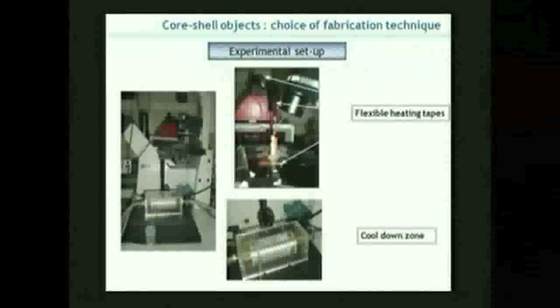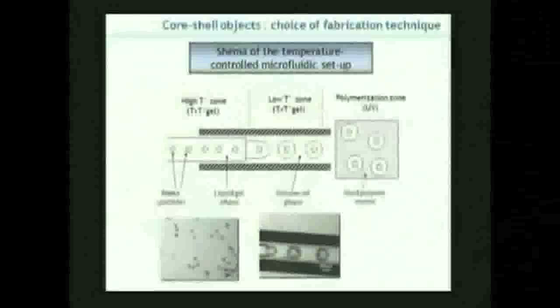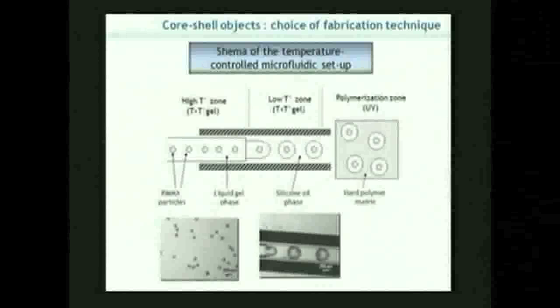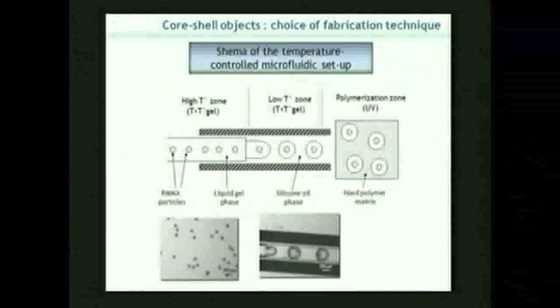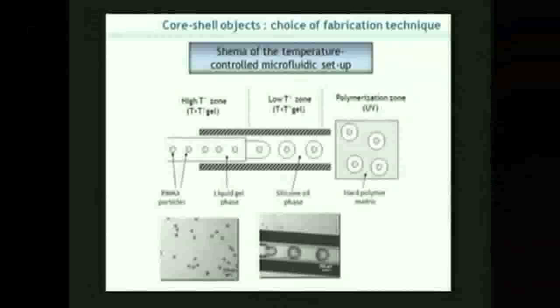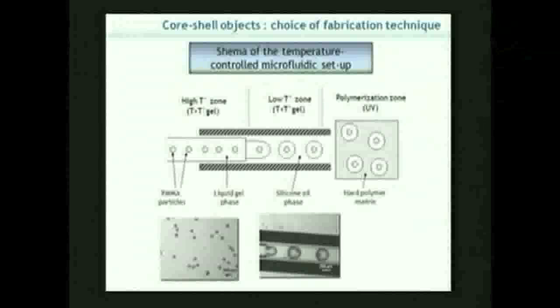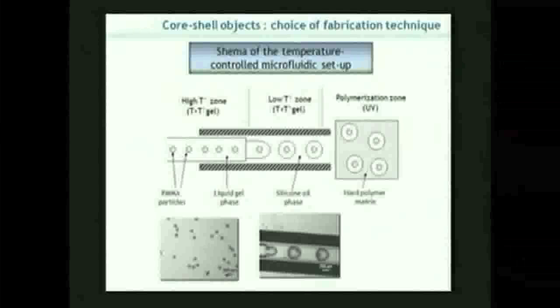And this here, okay, this is a schematic of the experimental setup. So let me go back here first. So you see, when you want to push the fluid containing the droplets, containing the PMMA particle inside the silicone oil phase, you want it to be fluid, okay? Otherwise you cannot push it through the capillary tube. So it should not be in the gel phase. So that's why we maintain this part of the setup at high temperature above the gel-liquid transition.